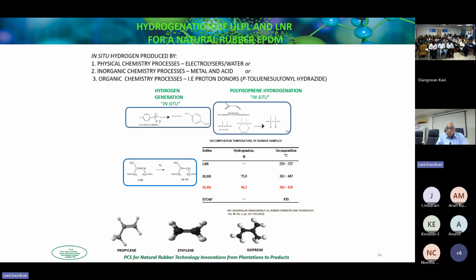But one thing is, you cannot do normal hydrogen gassing. That doesn't work. You have to have in situ gassing. You generate the hydrogen in the latex, and it reacts in situ. So that requires special treatment of the latex to keep it stable during the process.